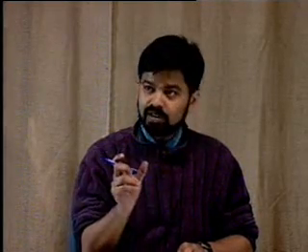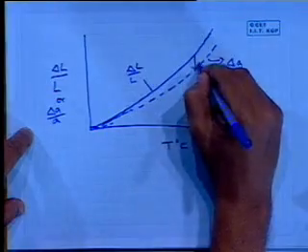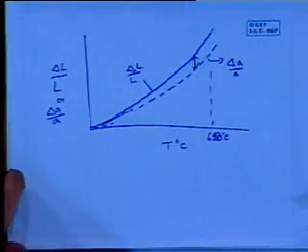The lattice constant that I'm measuring is an average value and therefore is not affected by the presence of vacancies. The X-ray can't detect it. So it gives me the true lattice constant and does not account for vacancies. Whereas the macroscopic measurement, how much the block has actually expanded, is going to tell me how many vacancies are there. And so at a given temperature, I note the difference between these two.